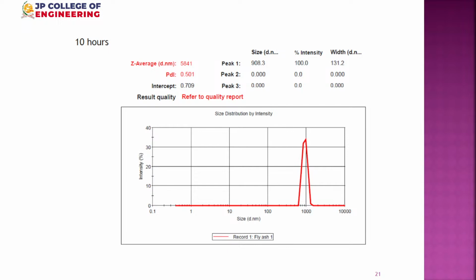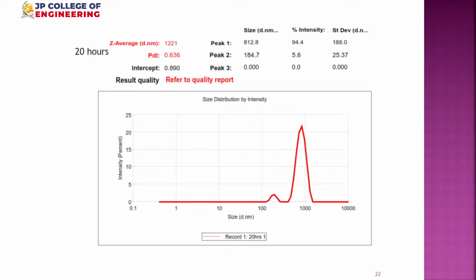Then on doubling the milling hours, next slide, please. We could now decrease only a little bit further. You can see the peak one, say 800 nanometer. So on 20 hours we get 800 nanometer. Next slide, please. On increasing the ball milling hours further, to around 45 hours, we could achieve almost nearing 700 nanometer.